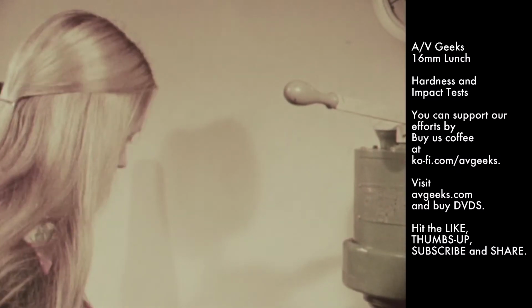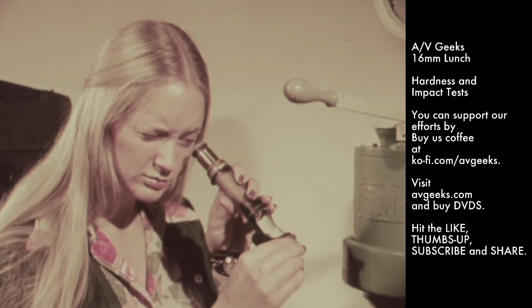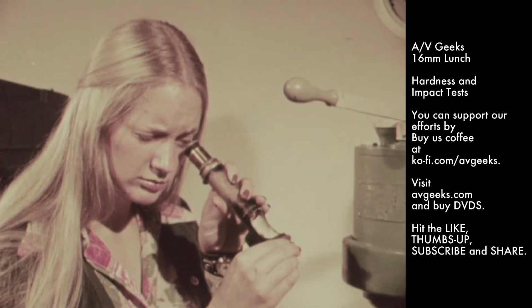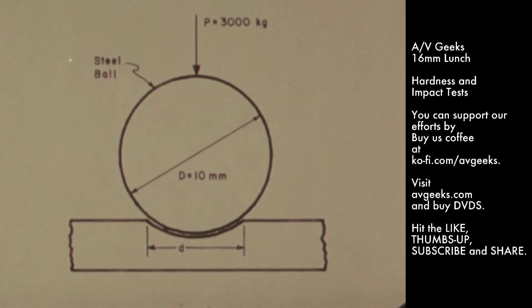A special microscope is used to measure the diameter across the top of the indentation. The Brinell hardness number is then calculated by dividing the applied load, 3,000 kilograms in the standard Brinell test, by the spherical area of the residual indentation.